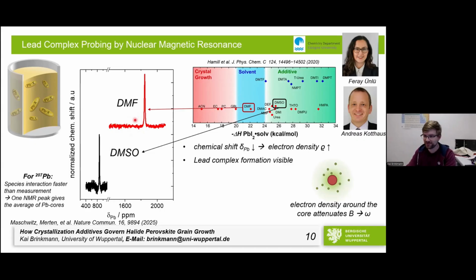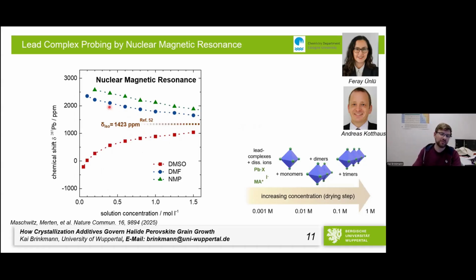So until then, we were quite happy. If you do this over concentration, and if you start out with different solvents, DMF, DMSO, and NMP, and then increase the concentration, going from the left side to the right side, we see all of these lead NMR signals approaching each other, which we interpret as a confirmation of what we've seen before. We start out with small complexes that have a lot of solvent around them, which look more like the solvent complex actually.